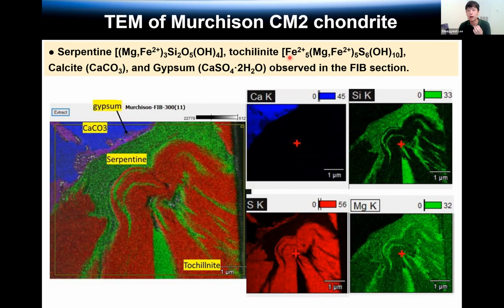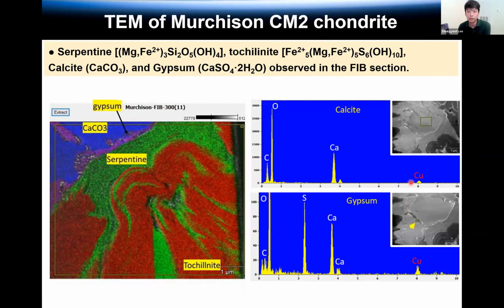But tochilinite has iron, magnesium, and sulfur, and structural water. The sulfur is important. So this red area is a tochilinite area. Also, gypsum has sulfur, so this area is a gypsum area. And the calcium area leads to the calcite and gypsum area. From the EDS mapping, we can extract the EDS spectra. So this is calcite and gypsum